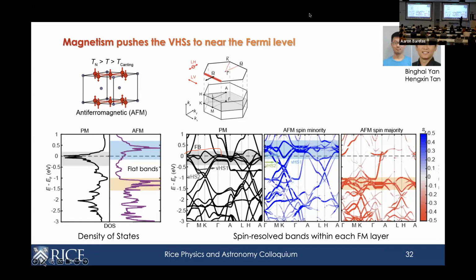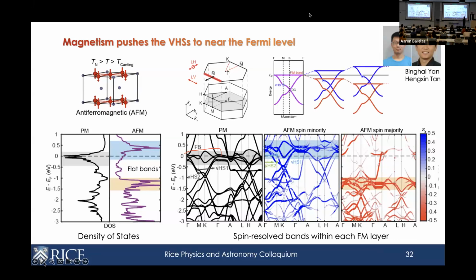Well, if you take this crystal structure, you think about each layer. Each layer is ferromagnetic. What does that mean? Let me illustrate this with a simpler picture. So here, this is a tight binding calculation. If you're high above the magnetic order phase, you will see that each state has a mixture of spin up and spin down, and those states have the same energy. But if the spins become ordered, then the spin up and spin down states can no longer be degenerate. So what happens is you can have a splitting of the bands going up and down, right?